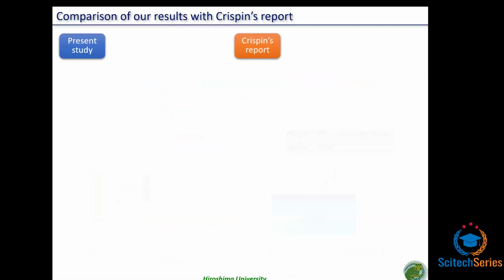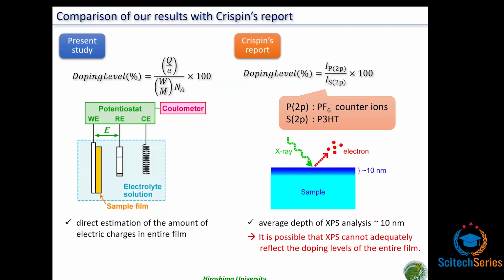At present, we think that these differences were formed by the different estimation method of doping levels. In our method, we can directly estimate the amount of electric charges in the entire film. On the other hand, Crispin uses XPS analysis and estimates doping levels using the ratio of the intensity of phosphorus and sulfur signals. However, XPS analysis is normally used for the surface analysis of materials, and the average depth is around 10 nanometers. Thus, it is possible that the XPS analysis cannot adequately reflect the doping level of entire films.